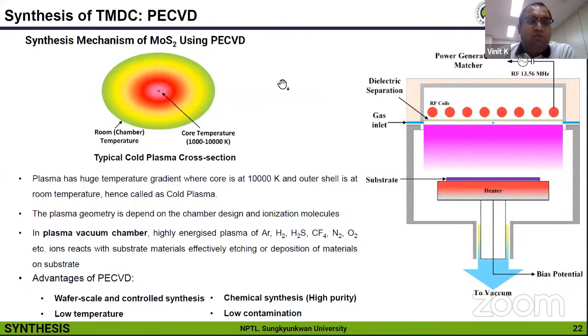So how does the plasma help us, or how can we reduce the temperature? If you look at a typical cold plasma, or any plasma cross section, its core temperature is much higher, up to 10,000 Kelvin, and the outer shell is at room temperature. Due to this unique structure, we can synthesize many high temperature materials at relatively cold conditions using this method.